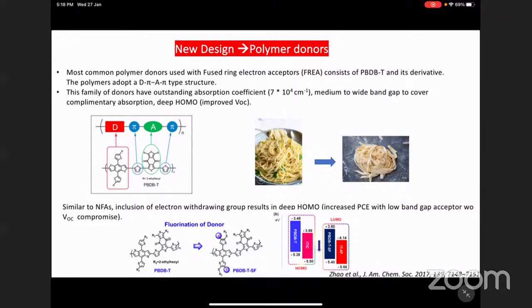Those are hybridized CT states because the LUMO offset has reduced. So that basically makes the charge transfer state stay much longer than what used to be the case with the fluorine. But still, they are able to do very good charge separation, because now we are not playing with spaghetti, but we have flat noodles. Those flat noodles have very highly delocalized charge transport states, which eventually make the charge transfer exciton very big, and you see the charge separation.